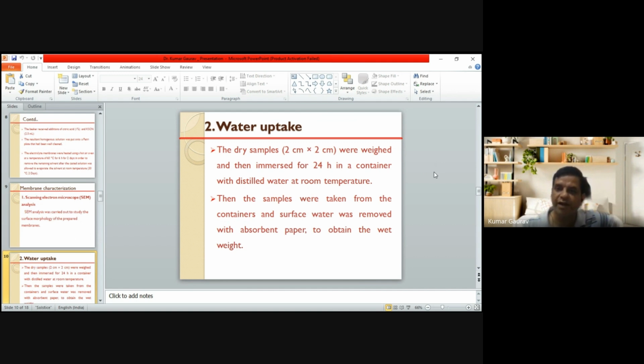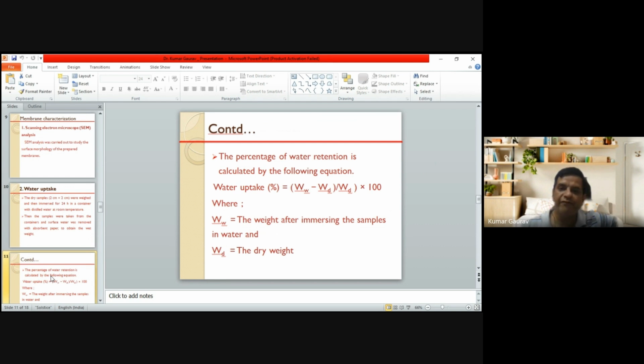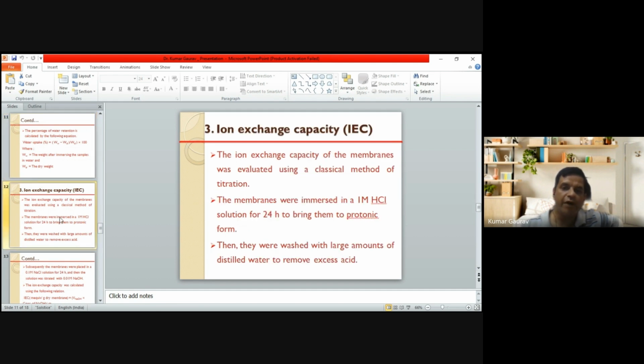For water uptake, we took the dry sample and immersed it for 24 hours in a container with distilled water, kept at room temperature. After that, the surface was wiped with absorbent paper and we got the wet weight, and we can measure the water uptake. Water uptake is W minus WD divided by WD, multiplied by 100. After that, we checked the ion exchange capacity.